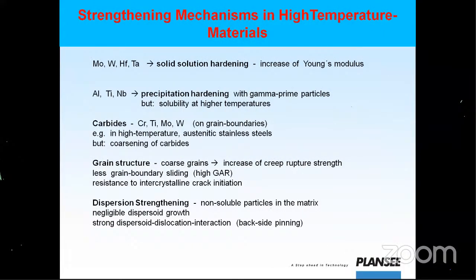Then, how do you make a high temperature material? We have 2-3 techniques available. First of all, we go for solid solution strengthening, like in the example of your cobalt alloy Haynes 25. There molybdenum, tungsten, hafnium, everything has been added to give solid solution strengthening, and it is not heat treatable. You can use it as is. It will work up to 1100 to 1150 degrees centigrade without much issue. With a coating, it can go up to 1200 degrees.